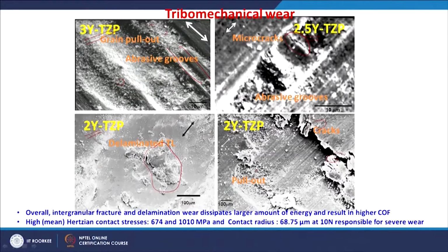If you look at the initial Hertzian stress, the mean Hertzian contact stress varies from 674 to 1010 MPa and the corresponding contact radius is from 68.75 micrometers, when calculated at 10 Newton load for this combination of different zirconia ceramics versus the steel material. So, you can see such a severe contact stress leads to severe wear. There is a change from grain pullout and abrasion to delamination of a tribo layer.